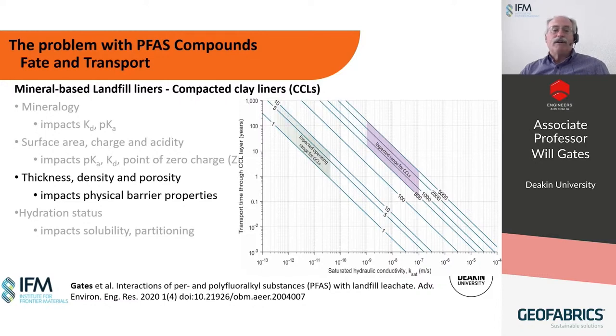From purely physical transport, to limit PFAS to 30 years or so, a compacted clay liner must have a saturated hydraulic conductivity in the low 10 to the minus 9s or lower, or have a thickness approaching 5 meters. Now, I think you will all agree with me that a 5-meter thick compacted clay liner is pretty much impossible, certainly not economic to produce for a landfill.